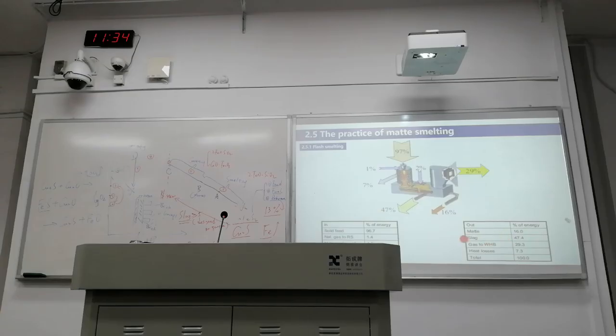And besides this one, this is a solid loss. You cannot change it because the slag is so important. So we are not changing the slag composition, no. Temperature, no. Then nothing can be changed. It's a big volume. And for the matte phase as well, the composition is fixed and the temperature is fixed. So you are not changing it anymore. So only 2 parts: one is the gas phase, one is heat loss.